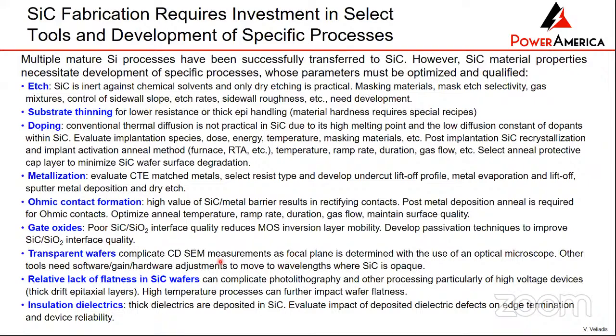Another consideration with silicon carbide wafers is that because of their band gap, they're transparent, whereas silicon, because of its lower band gap, is opaque. There are a lot of tools in the foundry that use photonic beams to inspect the wafers. Tools made to do inspection for silicon will not work for silicon carbide because the wafers are transparent. That's another area of consideration. Another issue is that silicon is a very streamlined, almost zero defect type of wafer. It's very, very flat, and that's not the case in silicon carbide. And in silicon carbide, you don't have a good thick thermal oxide layer that you can create, unlike silicon. So you need to deposit oxides and dielectrics, and deposited dielectrics contain defects. You need to be aware of that and work around it.